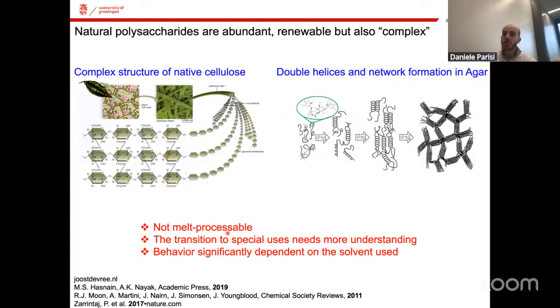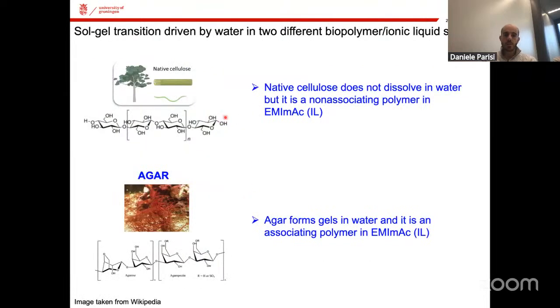So the transition to special uses, of course, needs more understanding, and something that is very different from standard synthetic polymers. Their behavior changes completely depending on the solvent that we are using. Let me just say that native cellulose does not dissolve in water because of the strong hydrogen bonds occurring between neighboring cellulose chains. But usually imidazolium-based ionic liquids are able to dissolve cellulose at the molecular level. Whereas agar has a very different hydrophilicity or hydrophobicity, because agar can in fact be dispersed in water, and it can form gels in water.